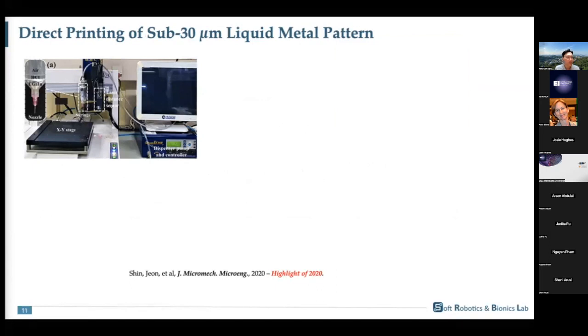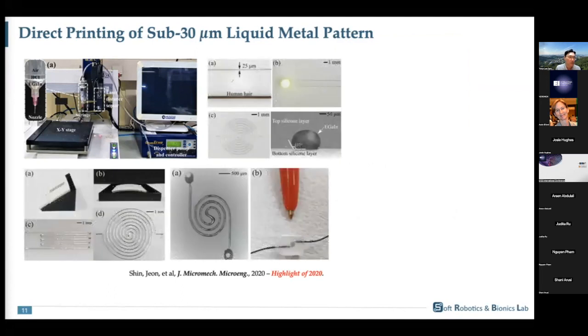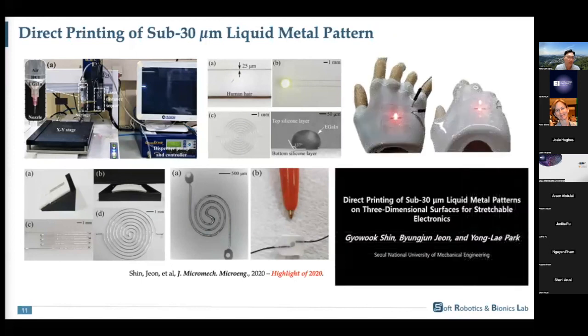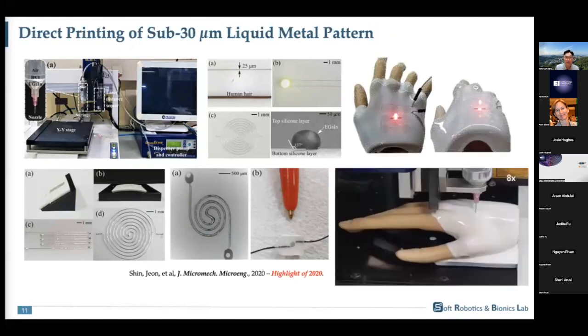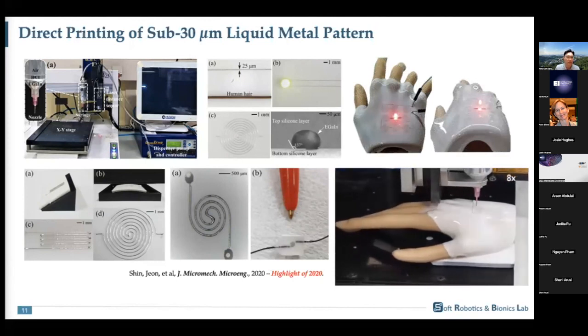The system has a motorized XYZ table and pneumatic dispenser. And using this system and by optimizing the parameters, we were able to draw a liquid metal trace as thin as 25 micron. And then, as you can see in the figures, we were able to draw these liquid metal patterns on an angled surface or curved surface, and really, really small sensors we were able to make. And since we have laser distance sensors, we will also draw these liquid metal patterns on arbitrary 3-dimensional surfaces like this.